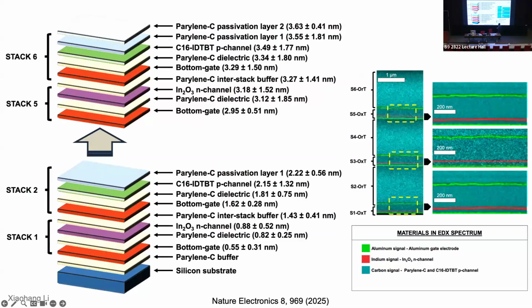Yeah, and then this is again a characterization of the interfacial roughness. So when you have different types of semiconductors in the same stack, technically it becomes much more challenging, right? Because those different semiconductors will require different processes and so on. So if you look at the bottom, stack number 1, the roughness is about 0.55 nanometer, right? So 0.55 is a very small roughness, because the distance between atom and atom is about 0.25 nanometer. So 0.5 nanometer is a very tiny roughness for electrons to move around.